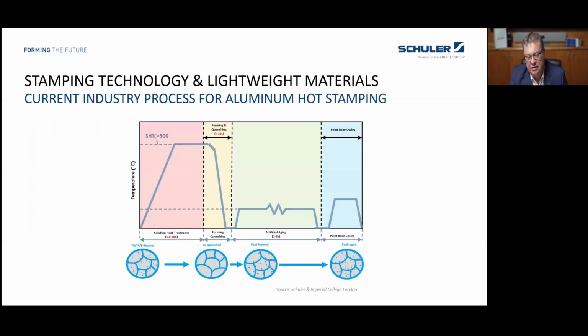So coming back to the aluminum hot stamping processes which are in use at the moment. This is a traditional forming process for aluminum. That means you heat up the high-strength aluminum 6 or 7 series material in a furnace, which could be a roller hearth furnace or a chamber furnace, but it needs some jet heating in order to get the heat into the aluminum, because the aluminum has a mirroring effect and it's very difficult to get to temperature just by radiation. So you have a special furnace to heat up the material. It takes 5 to 8 minutes to heat up the blank.